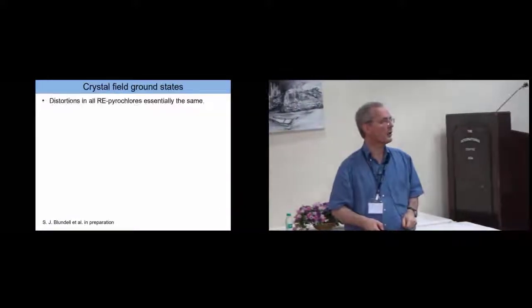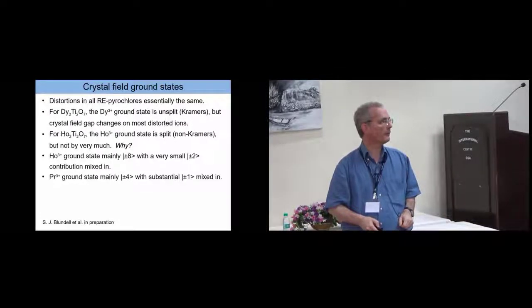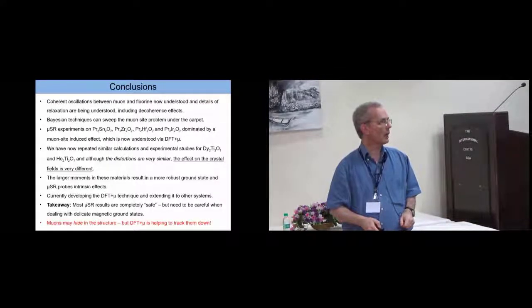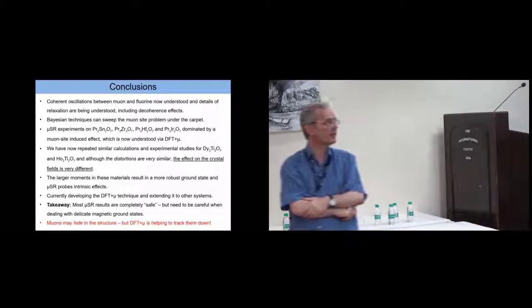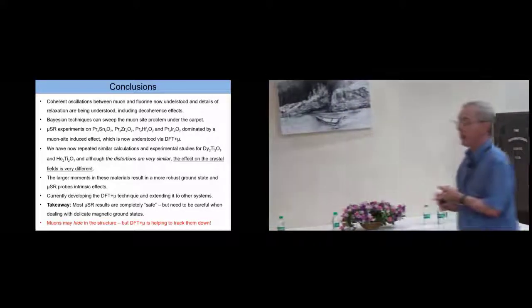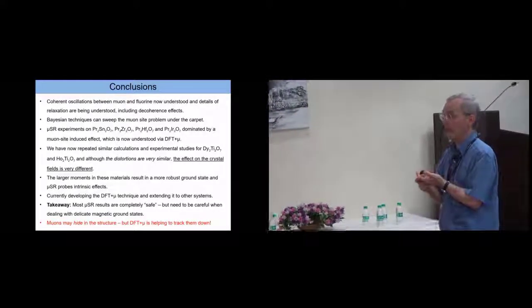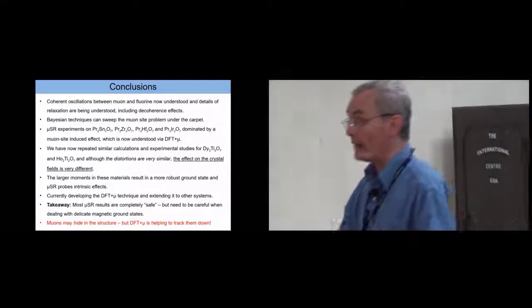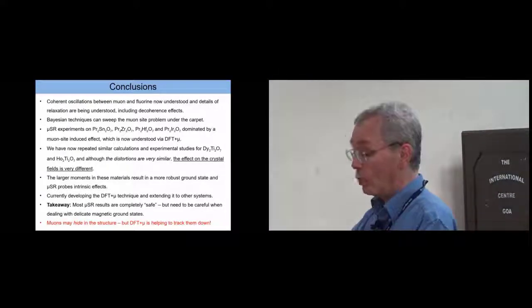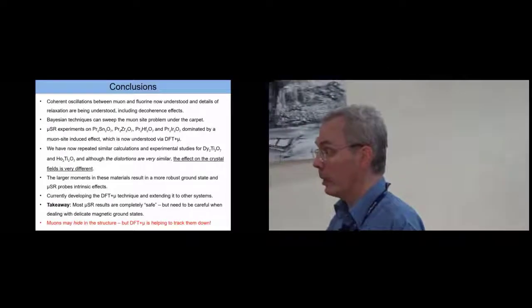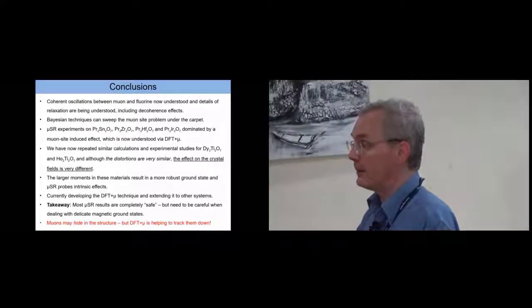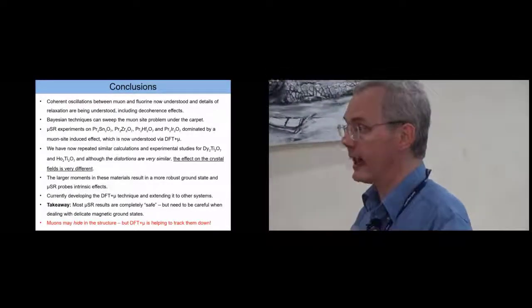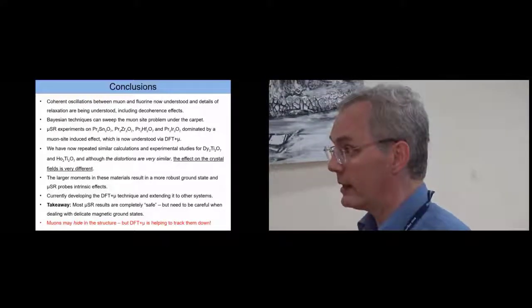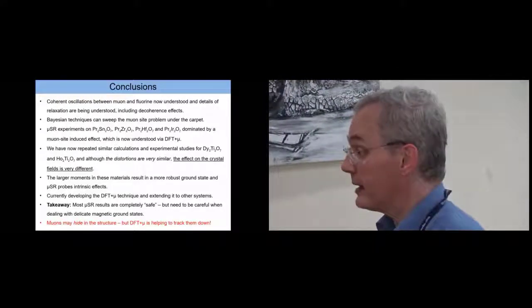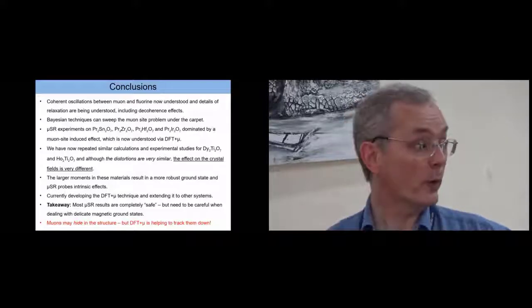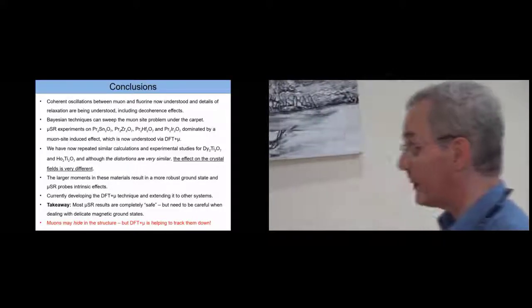So I'll come now to my conclusions. Essentially, I think this is my conclusion slide. We now have a number of ways of trying to solve the muon site problem. We either ignore it and use this Bayesian method. We use fluorine to localize the muon. Or we can now use DFT plus mu to really get very good understanding of what the muon site is, to understand the distortions. In most cases, the distortions have no effect, but we have now found one case where it does. So I'll finish there.